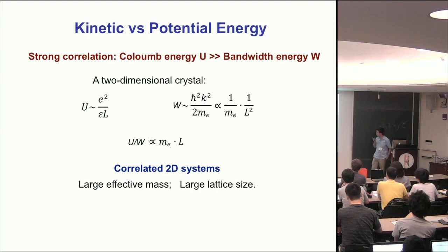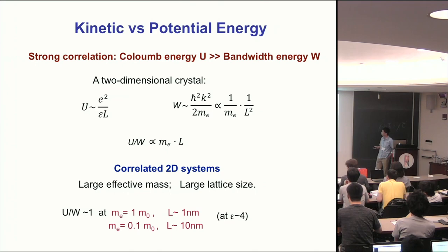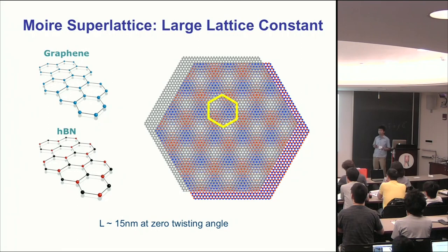The good thing about 2D heterostructures is that the large lattice size can be easily realized through the so-called Moiré superlattice. For example, if you have a piece of graphene and a piece of boron nitride, they both have hexagonal lattices with a very slight lattice mismatch of about 1%. If you stack them together with close to zero twist angle, a new periodic structure emerges determined by the lattice mismatch — the Moiré period. For graphene and boron nitride at zero twist angle, the Moiré period is about 15 nanometers. This large periodic lattice creates a Moiré potential for the electrons and gives rise to Moiré mini bands with very small bandwidth. This doesn't work well for monolayer graphene since it has zero effective mass — the worst case for engineering strong correlation. The choices are transition metal dichalcogenides, which are semiconductors with mass around 0.5 or larger, or going to ABC trilayer graphene.